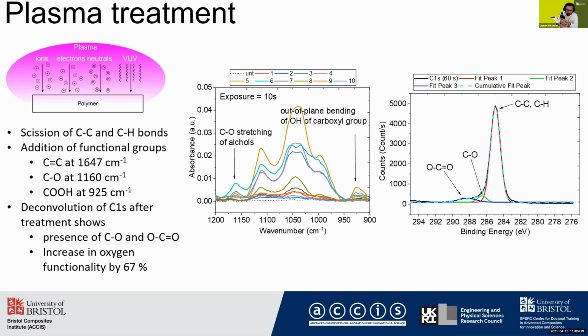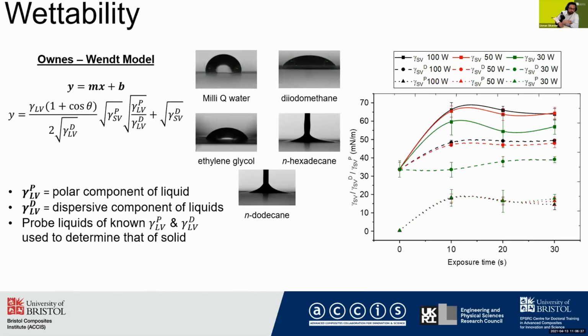We also did XPS to understand the percentage of oxygen content on the surface as a result of plasma treatment. And we found that if we deconvolute the C1s peak from XPS data, there was a 67% increase in the oxygen content as a result of plasma treatment.